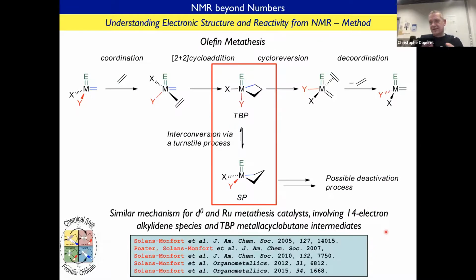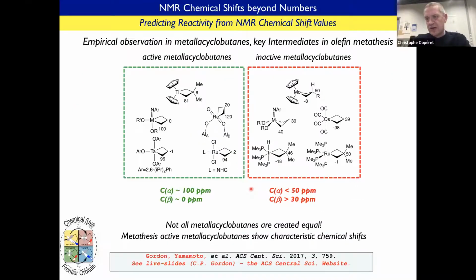So, again, because at MIT I have to discuss a bit about the work that we do a lot in collaboration with Professor Schrock. If you look at olefin metathesis, one of the key reaction intermediates is metallacyclobutane. And there were a lot of questions in the literature when we started that work about why a structure which has this trigonal bipyramid geometry is on the reaction path, and why this metallacyclobutane, which has a square pyramidal geometry, does not contribute to the reaction in olefin metathesis. And more importantly, what we noticed with my colleagues, Odile Eisenstein and Dick Anderson, is that all the metallacyclobutanes that participate in that reaction have a very specific type of chemical shift.